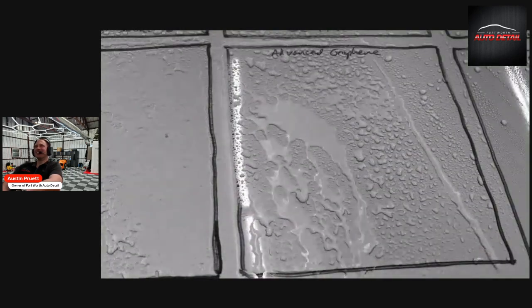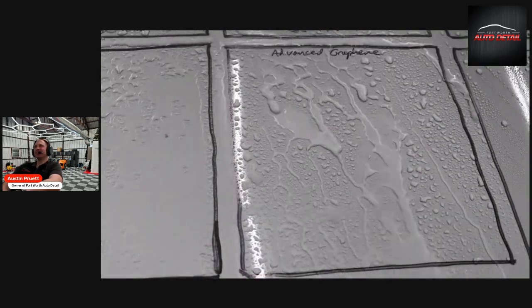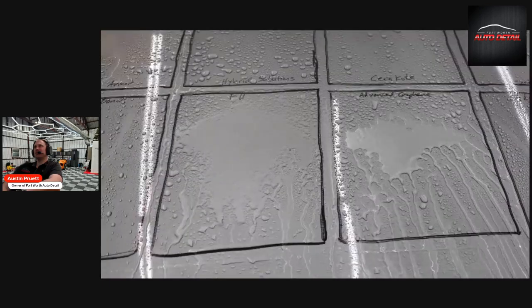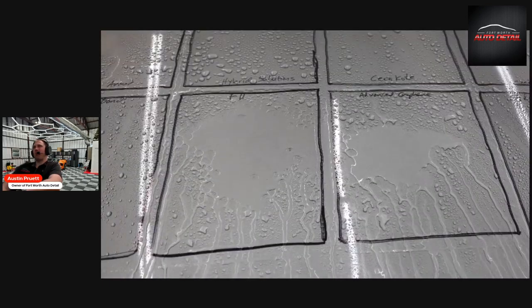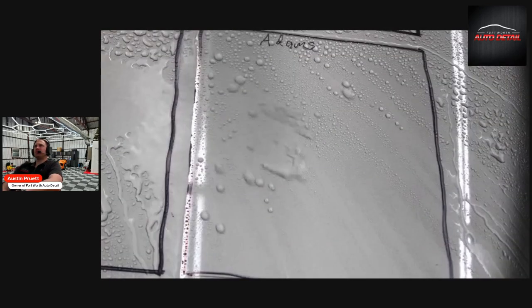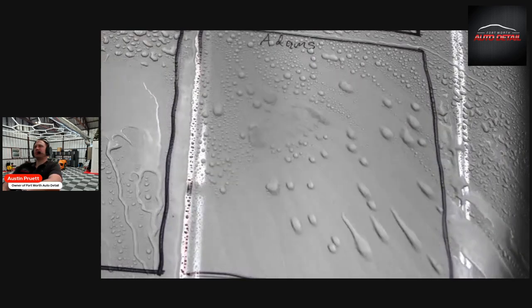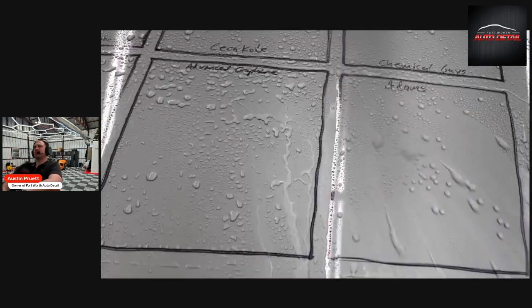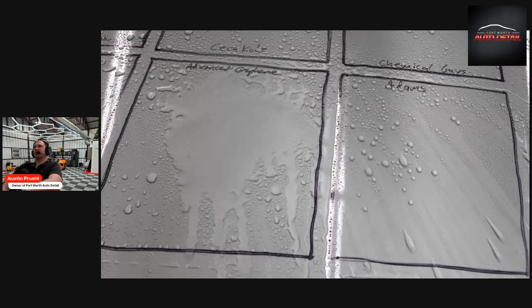And the Advanced Graphene is still performing well after the strip wash, but the water is beginning to form a sheet in some areas. However, the Advanced Graphene is definitely performing better than the F11. And the hydrophobic quality of the Adams after the strip wash exposure is by far the best yet. Between the Advanced Graphene and the Adams, it's not even close.